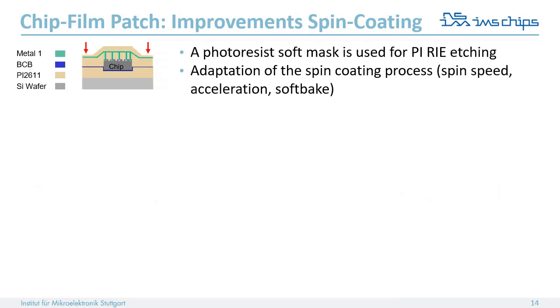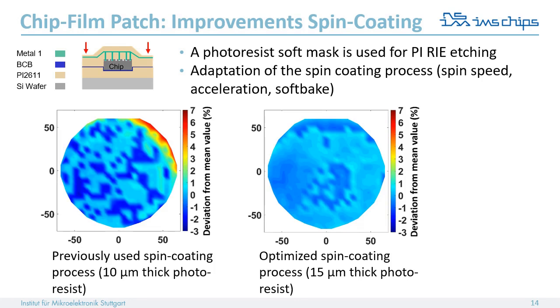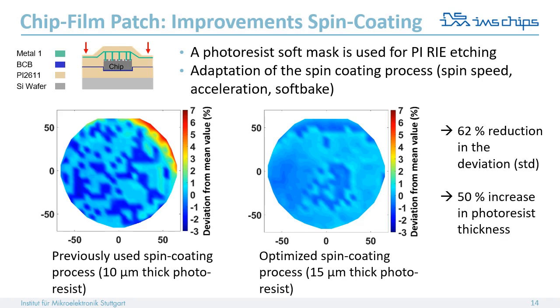Before, I mentioned that the polyimide RIE etching process is highly dependent on process steps, such as the spin-on coating. The focus is now on the area outside the chip, as indicated with the red arrows on the schematic cross-section here on the upper left side. In general, to open the fan-out pads on the wafer level, an appropriate soft mask is required to protect underlying structures. By adapting the spin parameters, such as reducing the spin speed to a minimum, and by reducing the acceleration, we have achieved a more uniform surface profile and furthermore a 50% increase in the photoresist thickness.